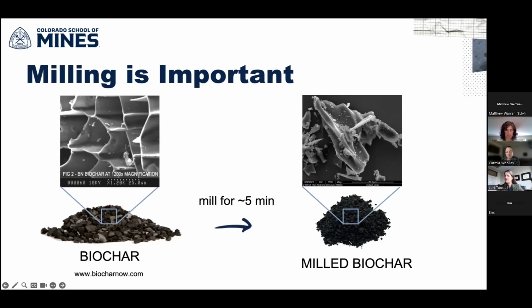It doesn't really want to be milled below a certain size, so the milling operation is really brief for what we've done. It's just about 5 minutes. We've primarily used a disc mill, and you get it down to a really fine powder, about 10 microns average particle size. It's a pretty low energy process, given that it's a brief operation. And then that's what we incorporate into our cementitious composites.